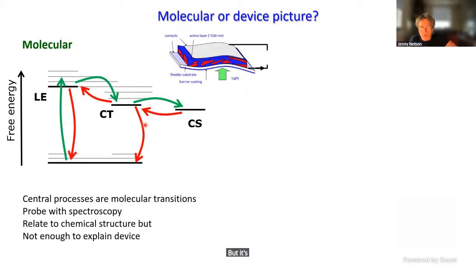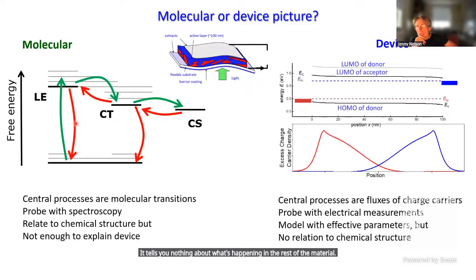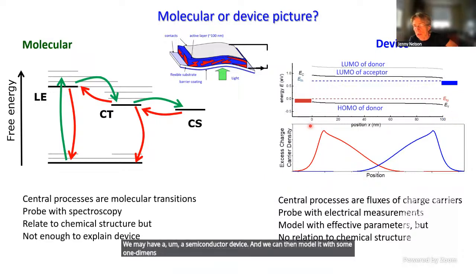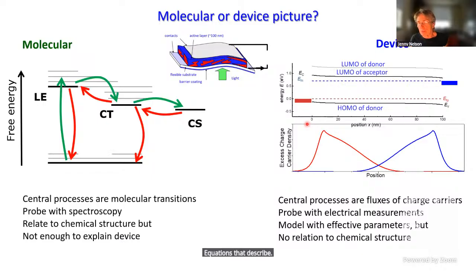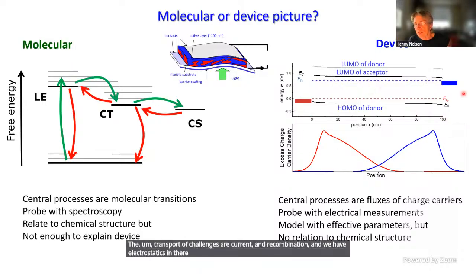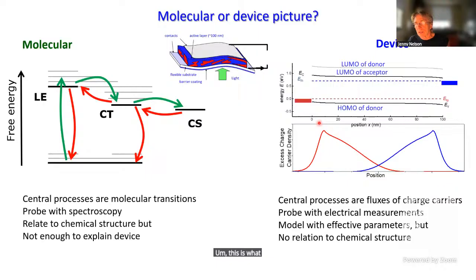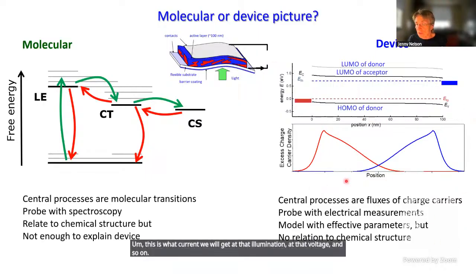But it's not really useful if you want to describe a device, because this kind of model of the interface tells you nothing about what's happening in the rest of the material. And then if we look at what's commonly done with semiconductor physics, we may have a semiconductor device. We can then model it with some one-dimensional model in which we have equations that describe the generation of charges, the transport of charges, the current and recombination, and we have electrostatics in there. And then we could solve this set of partial differential equations, and we could figure out, okay, this is what current we will get at that illumination, at that voltage, and so on. And that's commonly done with semiconductor physics.